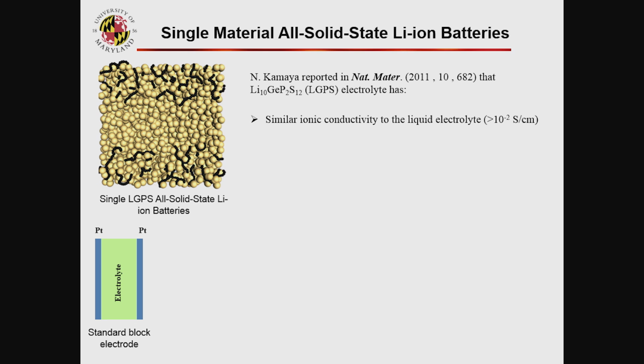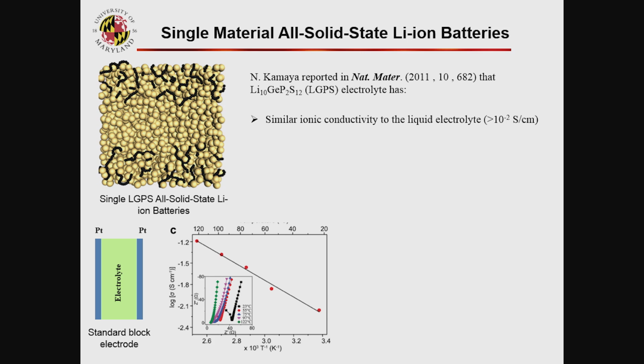And then we test. We synthesize the material. We use the blocking electrode, and we measure conductivity. That's true. We really got 10^-2. And then the second claim in this paper is that the stability is 0 to 5 volts. This is different from what I'm thinking, because I think they consist of cathode and anode components. It should not be stable in 0 to 5. And then we check the result. Why do we think the way that is different from this result?